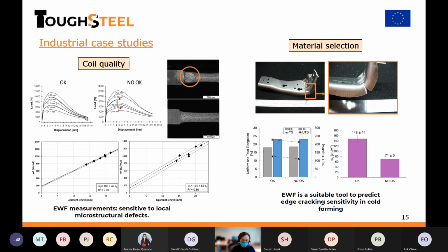So when testing them with the essential work of fracture methodology, we found that the okay one had some good linear correlation, but in the not okay one, we found some drops in the load. We can see here in the graphs, and that then led to scattering in the final results for essential work of fracture. This was related then to some brittle-like behavior in the surface of the fracture, and it shows that essential work of fracture measurements are very sensitive to local microstructural defects, which cannot be obtained with other methodologies.